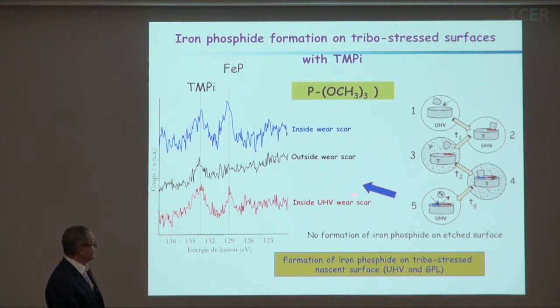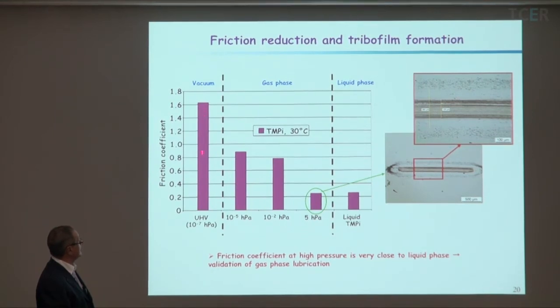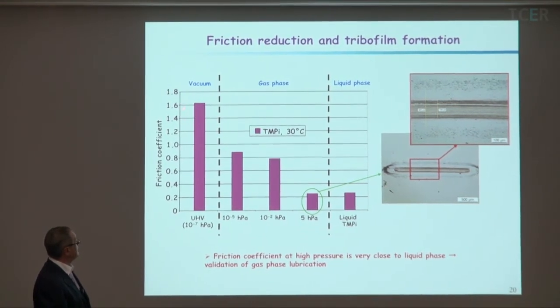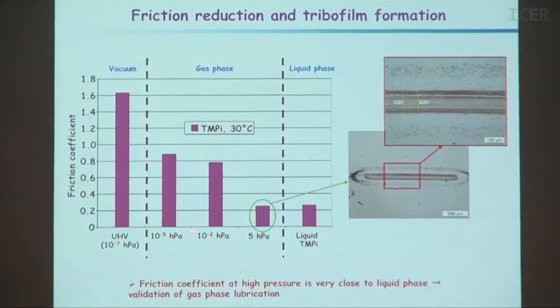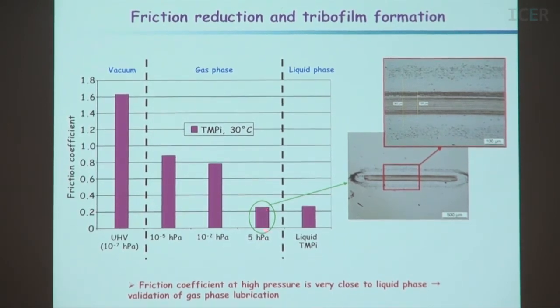And even inside the UHV wear scar, there is some phosphide also. So the additives can react with the tribostressed surface without any sliding. This is a very interesting case of the effect of a nascent surface. It's like a catalytic action. And this is the friction coefficient of steel in vacuum, very high friction. And we introduce the gas at different pressures. We increase the pressure, friction decreases here, at 5 hectopascal. And this is very close to the liquid if we make the test with the liquid, with the tribometer. So we have a good simulation of liquid phase lubrication by gas phase lubrication with some hectopascal of the gas.